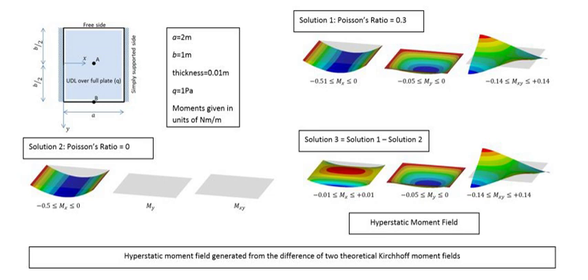These stress fields are often termed hyperstatic stress fields and they co-exist with the stress fields that balance the external forces. In linear elasticity, their presence is required to satisfy the strain-displacement compatibility requirements, and in limit analysis their presence is required to maximize the load carrying capacity of the structure or component. Such built-in stress may occur due to many physical causes, either during manufacture in processes like extrusion, casting or cold working, or after the fact due to uneven heating, or changes in moisture content or chemical composition. If the system can be assumed to behave linearly, the effect of preload can be accounted for by adding the results of a preloaded and a non-preloaded structure.